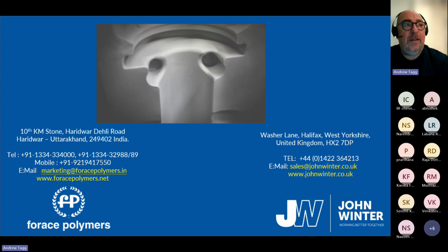If it's a GDC car wheel or four-wheeler, the same applies: adding the Tagg V to the area of the riser will assist feeding. Also, getting the right coating thickness. It's hard to describe without actually drawing it, but say you've got 5 or 6 risers around the top of the casting. It's beneficial to create a coating thickness that varies around the circumference, so you're effectively trying to create directional solidification back to the riser. Do you understand what I'm saying? That would be a way of doing it. But the first thing I would look at is using our Tagg V on the risers as a paste to create better insulation of the risers.